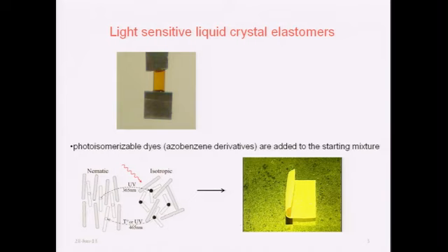We all know, this has been shown now several times. When we have a sheet of liquid crystal elastomer doped with azobenzene or any similar material, due to the decrease of the order parameter, it shrinks under light or UV light illumination. And if this shrinkage is inhomogeneous, which it necessarily will be due to the inhomogeneous profile of light and cis isomer concentration through the sample, it will change shape. In simple examples, it will bend, but other changes in shape are possible, as we have seen.